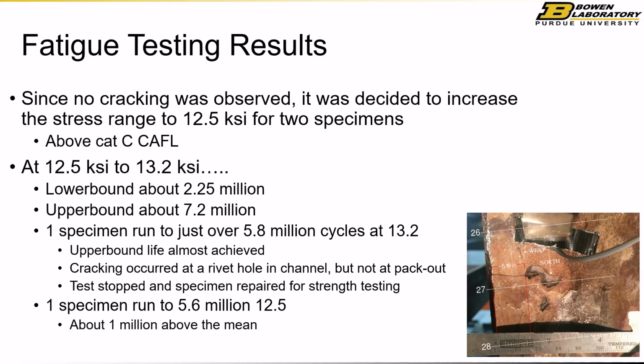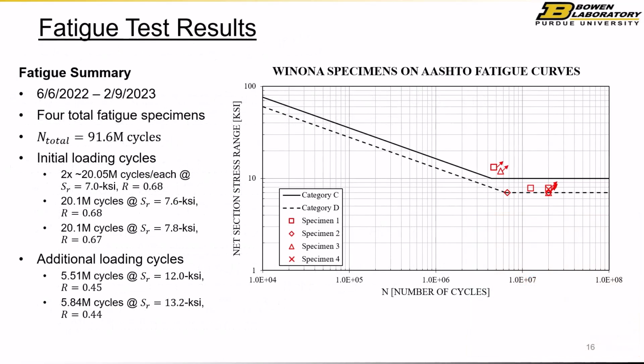Now you can combine all that data into effective stress range calculations, and this is the big takeaway. If you look at the data and you look at your category C or category D with the dashed line, either it's a run out, nothing happened, and again, these are all to the upper bound lives, or there was a crack, but it had nothing to do with the pack out. It was just a crack at a rivet hole. So why the good behavior?